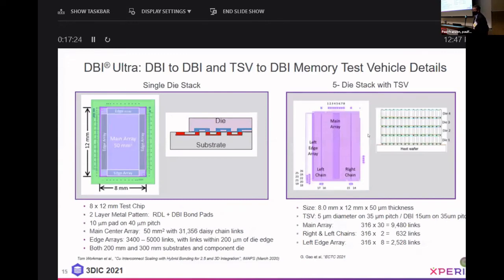So this shows our 2 test vehicles for memory. These both have pitches on the order of 35 to 40 microns. The one on the left is a single layer structure, which has a 40 micron pitch and a main chain in the center with about 31,000 links, and smaller chains around the periphery of the die. These chains come within a couple of hundred microns of the edge of the die. So we can evaluate some edge effects from that.